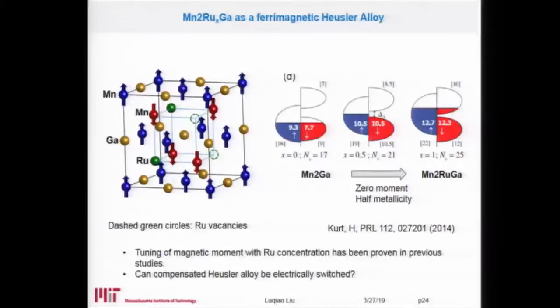We look into a system that is slightly different, which was also studied earlier by another group in Ireland. Basically what it shows is that in this compound, which is manganese 2, ruthenium X, and gallium, the magnetic moment is mostly contributed from two manganese sublattices. But those two manganese sites are different, because one manganese has gallium as its nearest neighbor, but for the other manganese, the nearest neighbor is ruthenium. So in terms of their crystal location, those two manganese are not completely equal to each other. So it also has reduced symmetry. That's the reason why it's a ferrimagnet instead of an antiferromagnet.